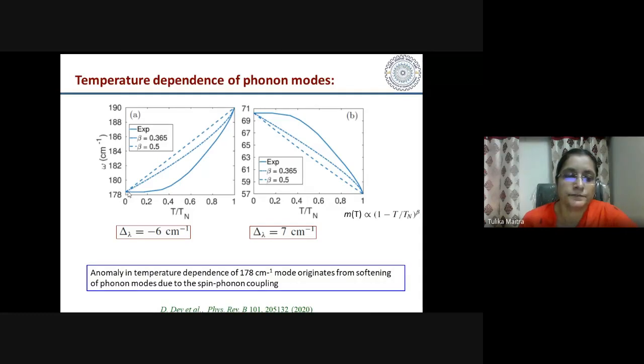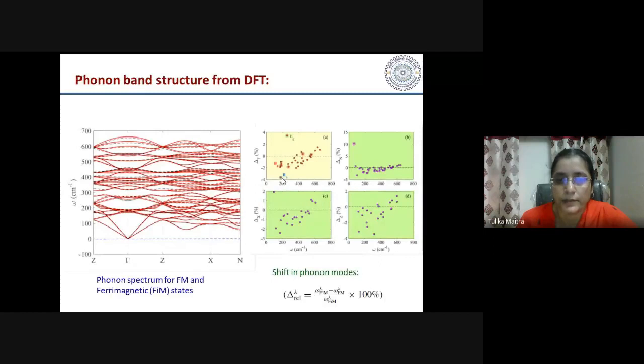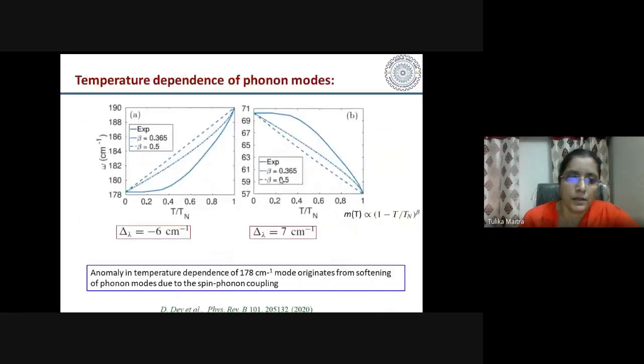So what we see here is that for this mode at around 180 centimeter inverse, which is this one, there is a softening of the phonon mode due to change in magnetic state. So this one gives rise to temperature dependence exactly like what we saw in the experiment for this 2 magnon mode, whereas this one, which is around 70 centimeter inverse, gives rise to a temperature dependence like that we have seen in the 1 magnon mode.